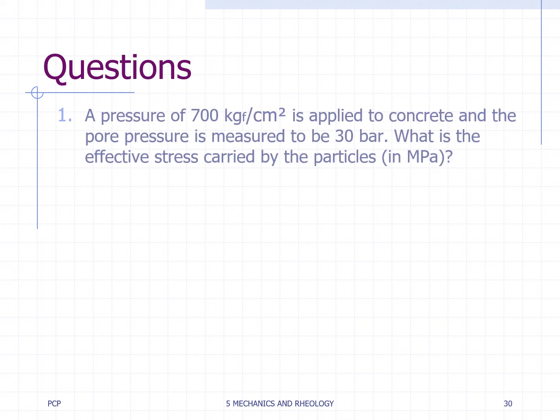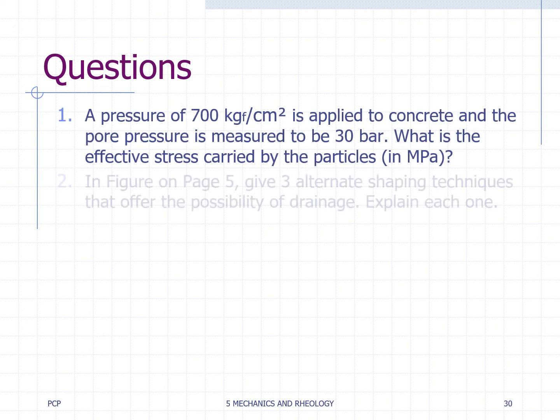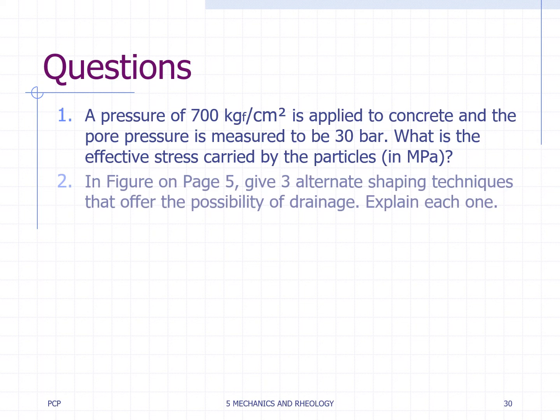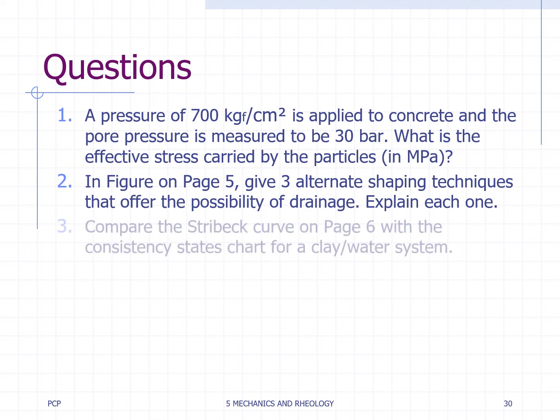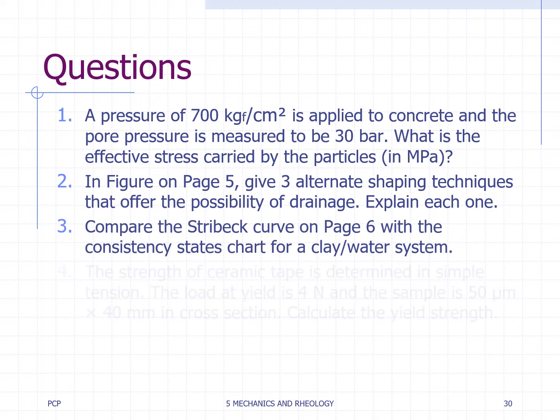A pressure of 700 kilograms force per square centimeter is applied to concrete and the pore pressure is measured to be 30 bar. What is the effective stress carried by the particles in megapascals? In the figure on page 5, give 3 alternate shaping techniques that offer the possibility of drainage. Explain each one. Compare the Stribeck curve on page 6 with the consistency states chart for a clay water system.